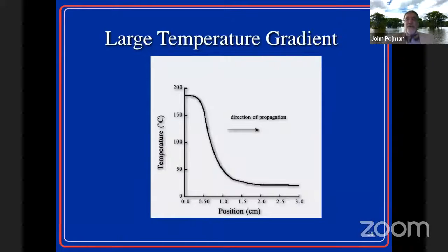So this is an example here of a mixture of acrylates. These are commercial products mixed with a clay to make it like a putty that can be molded. And there was a dye that changed color when it reacted. So you can see the reaction. And these are centimeter marks. So this is just propagating. We started it. Once you start it, it'll go no matter how long the sample is. And here it's now starting another reaction. So these experiments are extremely easy to perform with some systems. They're characterized by having a large temperature gradient. It can get up to over 200 degrees centigrade.